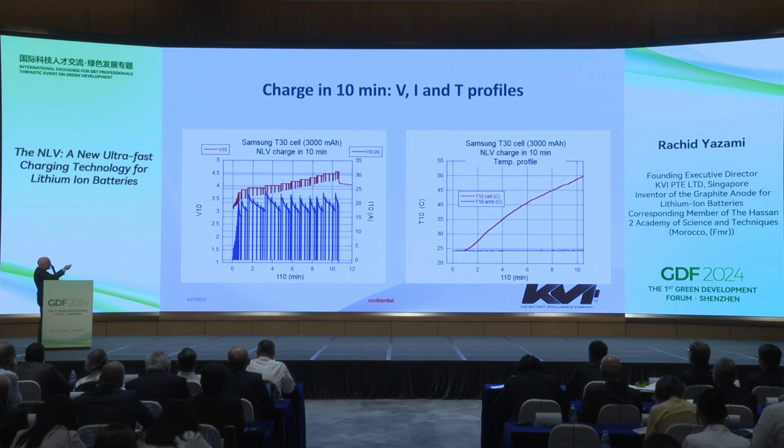And the interesting thing is, if you look at the right-hand side picture, the temperature during the 10-minute charging did not exceed 50 degrees. And Samsung put 60 degrees as the safety limit. So we are 10 degrees below the safety limit of this battery.